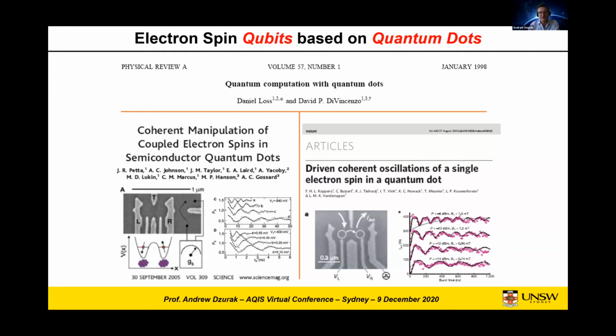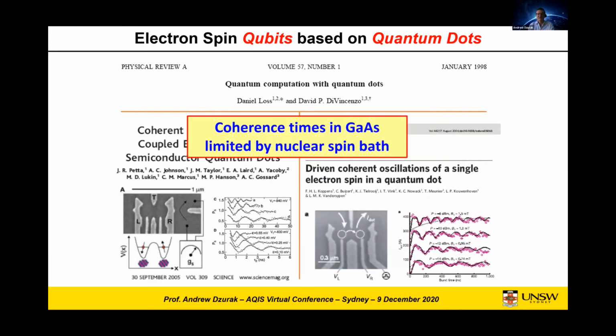Most work in the 1990s and the early 2000s focused on gallium arsenide for nanoelectronic devices and mesoscopic devices. However, a major problem with gallium arsenide is that there's no nuclear spin-free isotope of either gallium or arsenic. And so there's constant disruptions from the nuclear spin bath, which damages the fidelity. And although work has continued to use dynamical decoupling to improve fidelities, obviously by working in silicon, one can remove that issue and have a significant advantage. And so in fact, most of the groups who were originally working on qubits in gallium arsenide have now migrated across to study quantum dots in different silicon technologies.